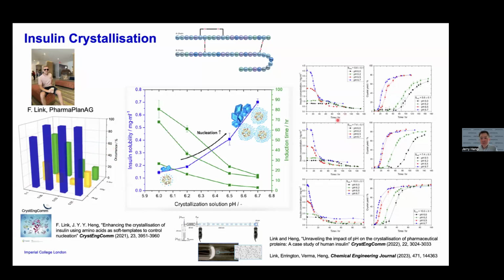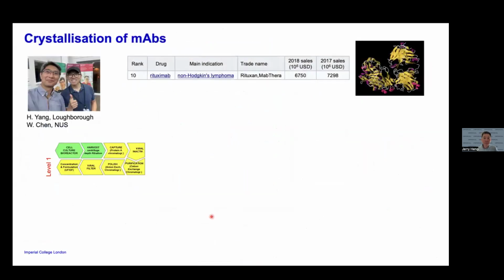What Fredrik was working on was to test out different pH conditions, and obviously here we demonstrate that insulin crystallization was quite sensitive to pH. Fredrik has also been able to transfer this into a slightly larger process, not only at milliliter or microliter scale, but into a somewhat continuous flow crystallization, where we demonstrate that the pre-mixing chamber is quite important in the crystallizability and crystallization profile of insulin.